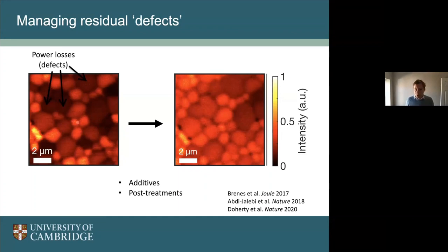And we've also been working on ways to treat these films and actually make them better. You can see this is one example where we've been looking at different additives and different post-treatments to the films, and you can see it's much more uniform spatially across the film, but also much more luminescent and much brighter. So in doing this, we've gotten rid of a lot of these defects and a lot of these traps that were there in the film.